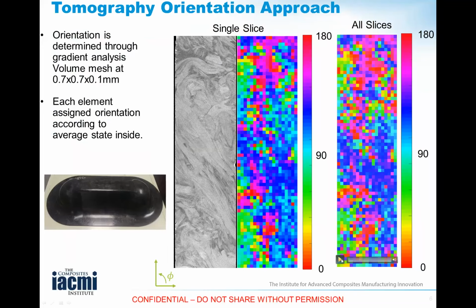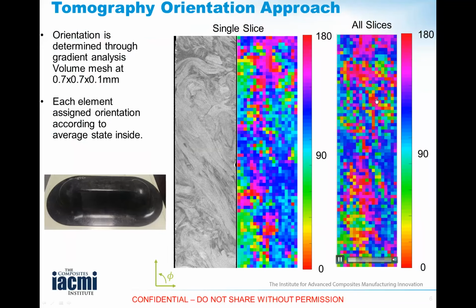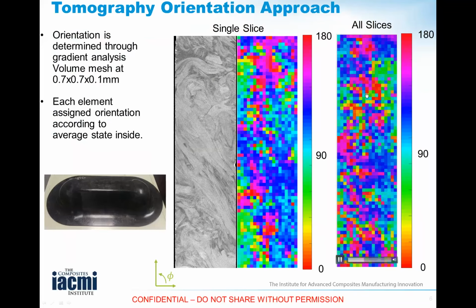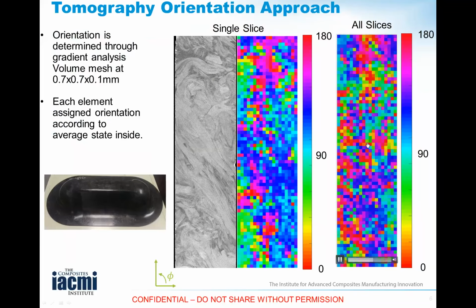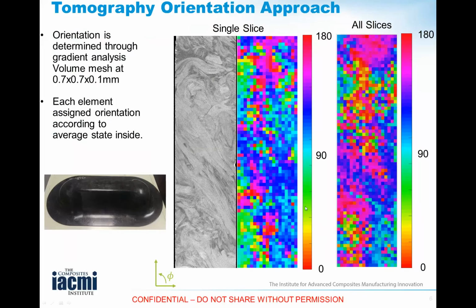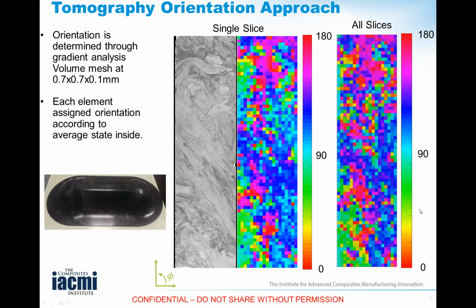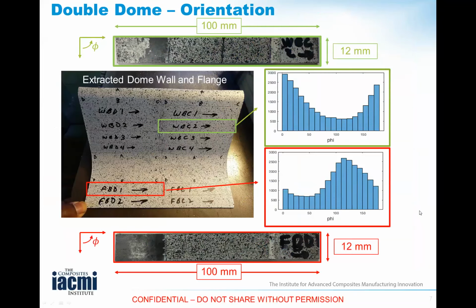If I were to play a real quick video, just to show you that now I can track the 3-dimensional orientation of these platelets through the thickness with this technique. So that's a grounding verification for platelet orientation using X-ray computed tomography.